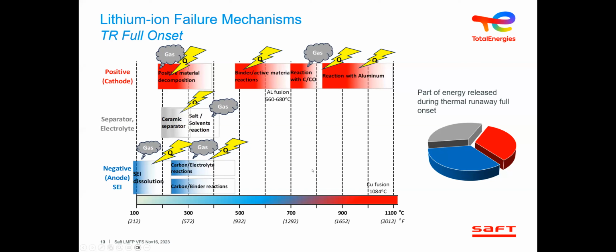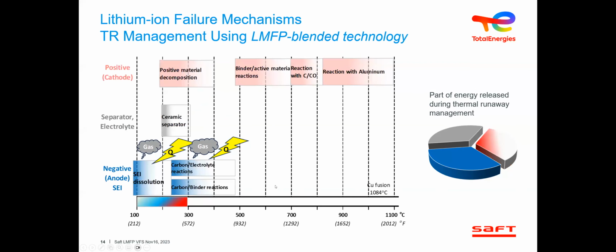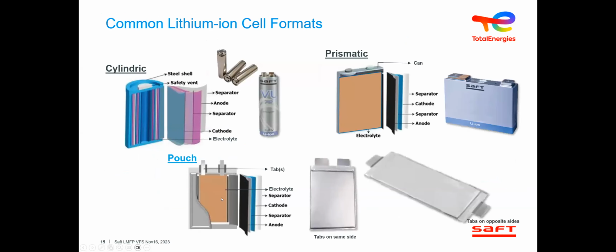And this is why you now see processes of handling thermal runaway through immersion, or trying to drown the battery module with water, and some strategies like that, or letting it burn. The benefit of having lithium manganese phosphates, or having a more stable cathode structure, is that you minimize a good third of these reactions. So you can concede degradation of your solid electrolyte interface, having some level of reactivity here. But if you have a strong separator and prevent that cathode from reacting, you can obtain a much more stable system. So this is what we've done.